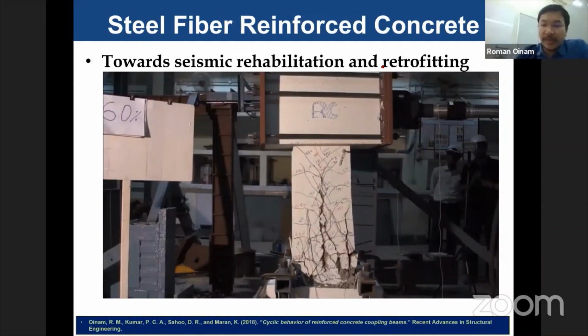So the damage was totally concentrated at this bottom region, and due to the steel fiber, the concrete spalling is limited. Here I did not show the plain concrete, but in the case of the plain concrete, most of the concrete is gone; it has already spalled out. But in the case of the steel fiber concrete, okay, there is some damage, but the spalling concrete is still very little compared to the plain concrete. So this is the advantage again.